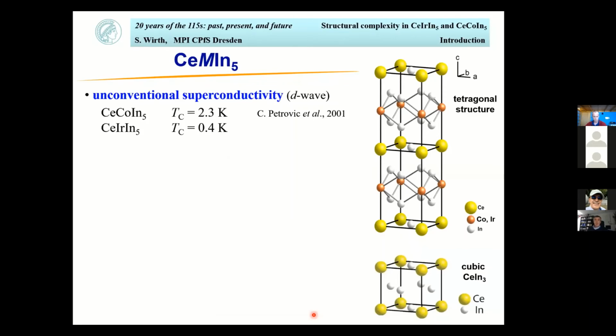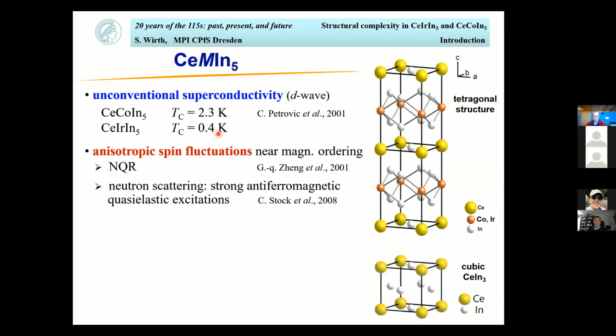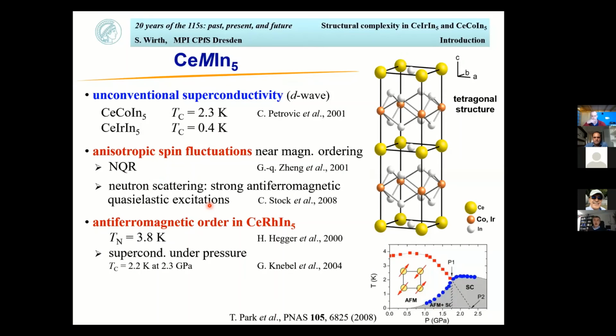Now, also the structure has been shown several times already, but that becomes crucial for my talk here. You all know the cobalt and the iridium variants are unconventional superconductors with the transition temperatures as shown here, but they are also close or near to magnetic ordering. And that has been shown by finding anisotropic spin fluctuations either in NQR or in neutron scattering measurements. And of course, the whole thing becomes much more prominent if you look at the rhodium counterpart, which is a Néel antiferromagnet with a Néel temperature of 3.8 Kelvin, and which gets superconducting here under pressure.